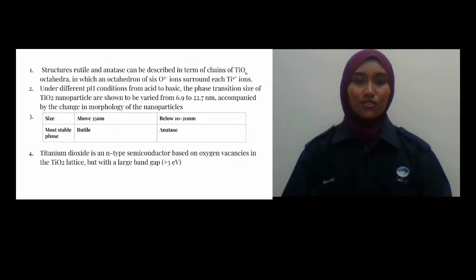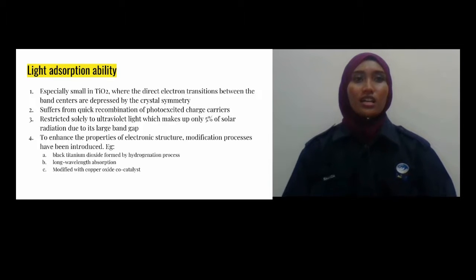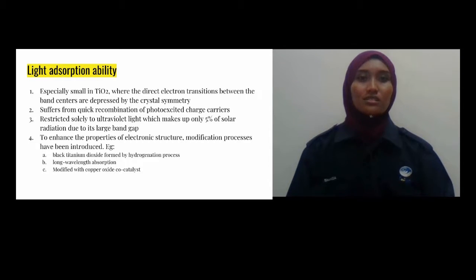Under different pH conditions from acid to basic, the phase transition size of TiO2 nanoparticles is shown to vary from 6.9 to 22.7 nanometers, accompanied by a change in morphology of the nanoparticle. Titanium dioxide is an N-type semiconductor based on oxygen vacancy in the titanium lattice but with a larger bandgap. Light absorption ability is also present in titanium dioxide, especially small in titanium dioxide, where the direct electron transition between the band center is depressed by the crystal symmetry. It suffers from quick recombination of photoexcited charge carriers. It is restricted solely to ultraviolet light, which makes up only 5% of solar radiation due to its large bandgap.